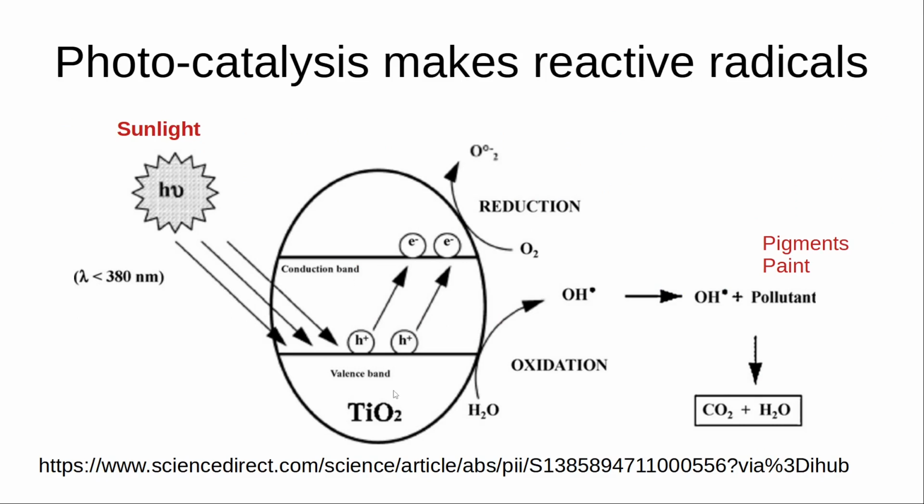Now going into a bit of heavy chemistry, you have UV light shining on your titania, your rutile or anatase. You see here's a valence band, so it excites electrons from the valence band to the conduction band. This H plus just talks about holes, and then your electrons are excited. Those excited electrons then react with your oxygen to form this type of radical, and your hole is then reacting with your water to form this radical. And these radicals then cause the degradation.